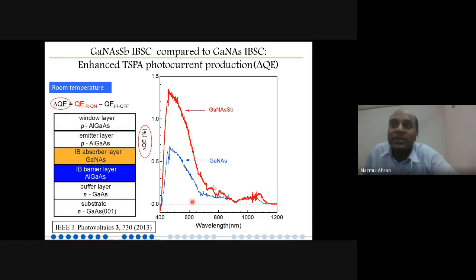But the message here is that if you look at the blue line, this is the material based on gallium nitride arsenide. They are only 0.5%. We can make only 0.5%; the efficiency is very low. I mean, for the 2 photon absorption, the long wavelength photons, we can convert only 0.5% of them to electric current.